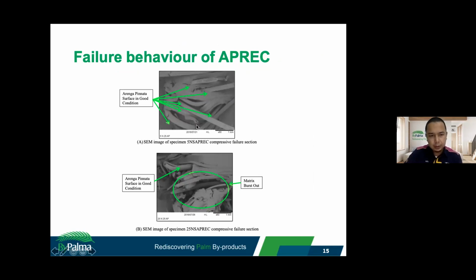As you can see, the Arenga Pinnata fiber detached from the epoxy matrix, while the fiber is still in good condition after the compression test. And then this is the second image, evaluated to identify why the composite has lower strength compared to the 5%.